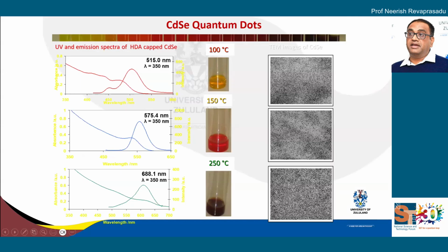So cadmium selenide quantum dots are one of the first materials that was widely studied. It was known as the kind of Cinderella material, having promising properties. And so a lot of the early work was done on cadmium selenide quantum dots. And you'll see here at 100 degrees, you can get photoluminescence at 515 nanometers. And you'll see in the absorption spectrum, it has very distinct features in terms of excitonic features.